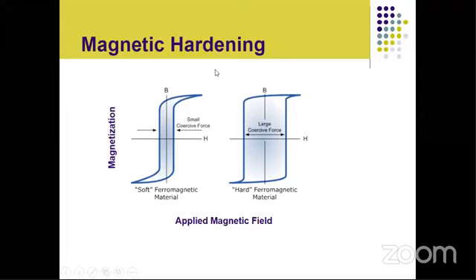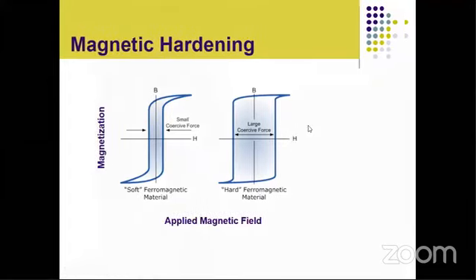If we have a ferromagnetic phase, then we must have some non-ferromagnetic or least ferromagnetic phase, so that the ferromagnetic phases are separated by non-ferromagnetic phases. If such a structure is developed in the magnets, then we can get the maximum coercivity and good magnetic properties of these alloys. Actually, this is one of the phenomena. Other families of magnets have other different phenomena. But in this case, we will try to develop ferromagnetic phases and least ferromagnetic or non-ferromagnetic phases alternately, and these will contribute towards the hardening of this material. And finally, this material can be used as a permanent magnet as we desire.